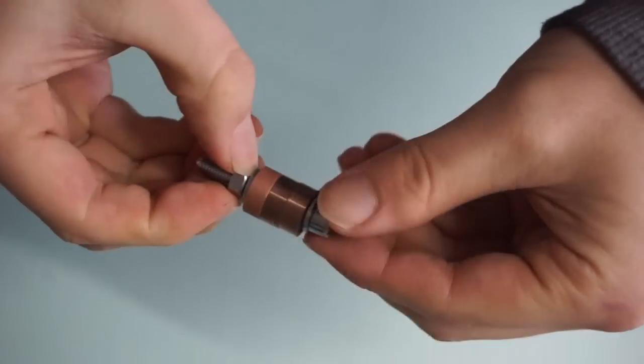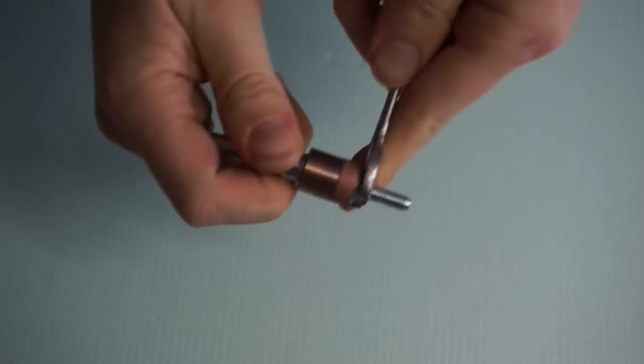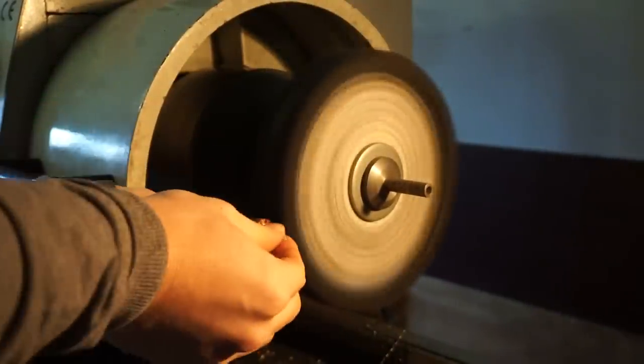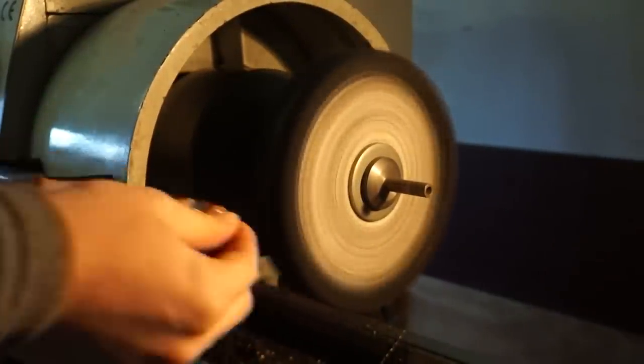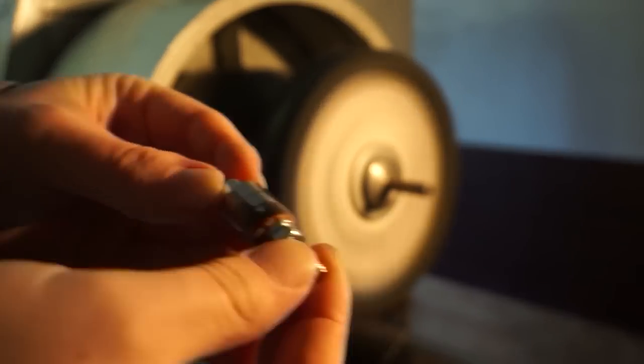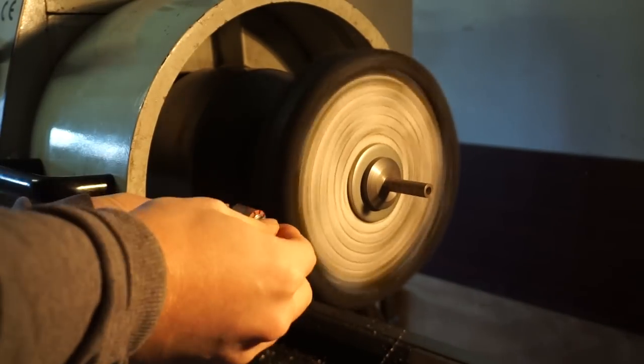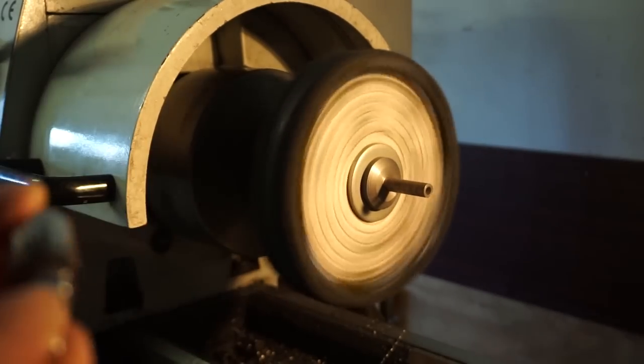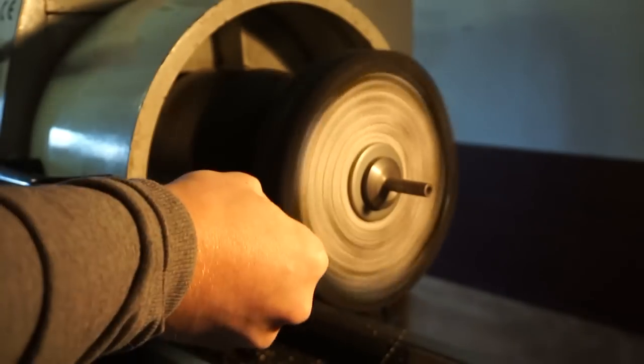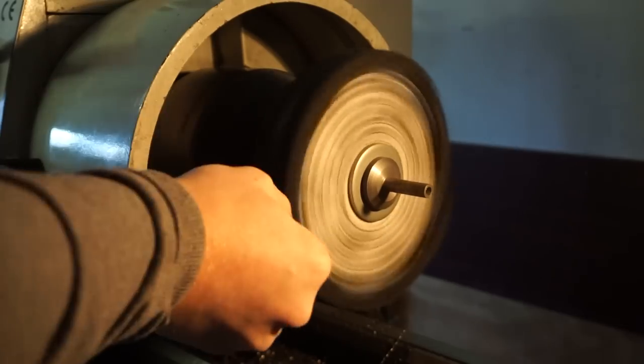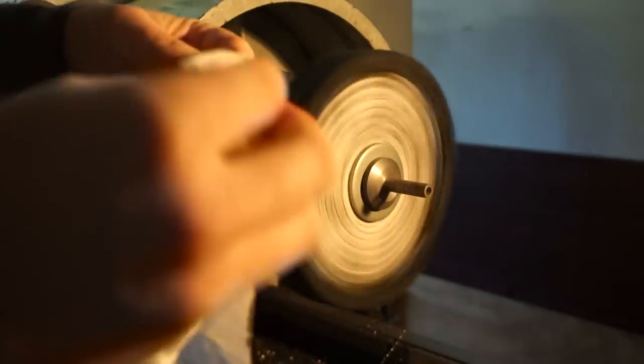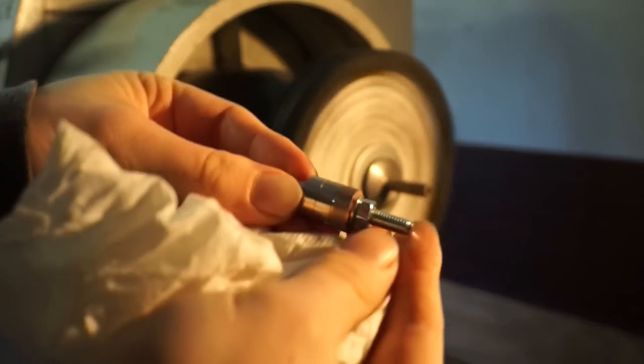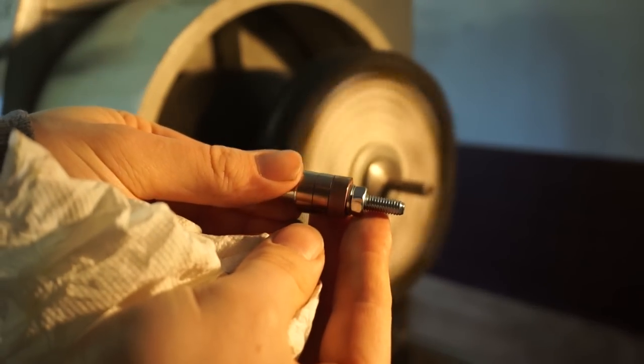Unfortunately I have no way of testing the thickness of the coatings but I really wanted to see the differences in durability. Therefore I mounted the three test pieces onto a screw and took them to the polishing wheel. It had some polishing abrasive on it. Even the first run of polishing proved how thin the layer was. Unfortunately the camera does not show that particularly well. I polished the stack of rings a little more so that all of the pieces showed blank spots.